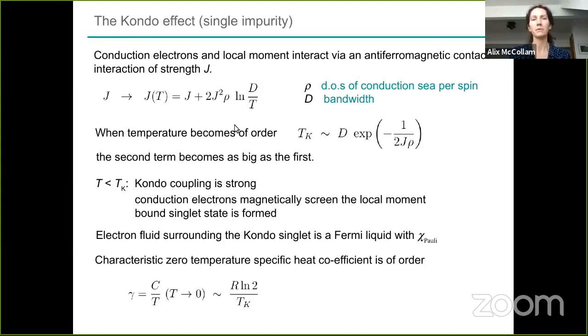And when you change the temperature, so if you look at the strength of this coupling as a function of temperature, when you get to a temperature that is approximately this size, then the second term becomes about the same size as the first term, and then you can't treat this as a perturbation of this anymore. So it becomes more important in the behavior of the system. So this temperature is a kind of a division between a high temperature region where you have local moments and conduction electrons not doing very much to each other. And then at lower temperature, below this temperature, you have a stronger interaction. So actually you get the formation of a bound state. The interaction is strong enough that you get singlets forming between the local F moment and the conduction electrons. So a strong coupling, you get a singlet state.